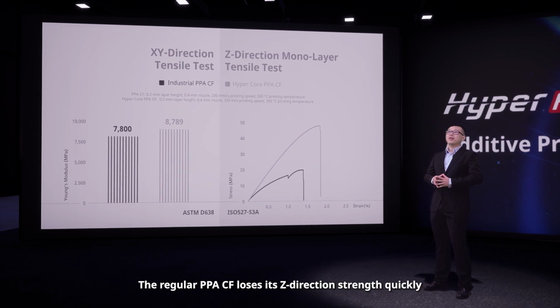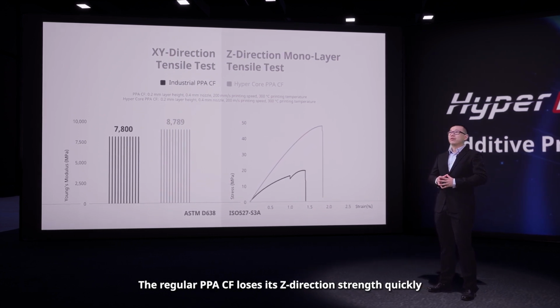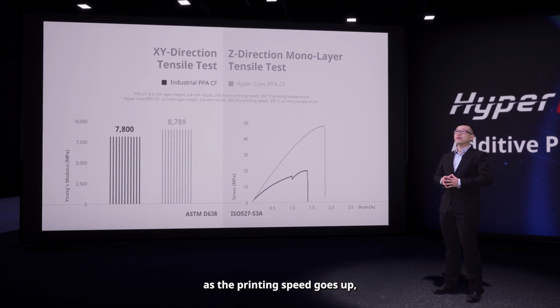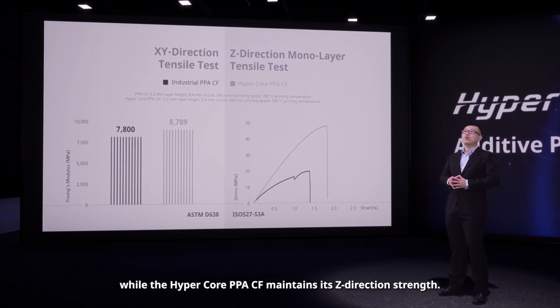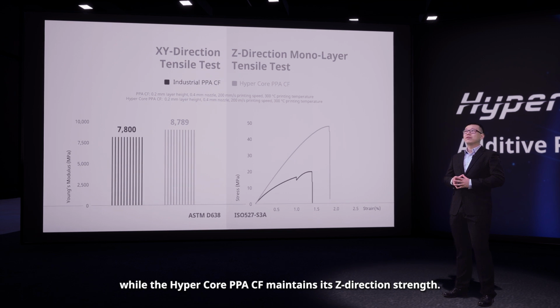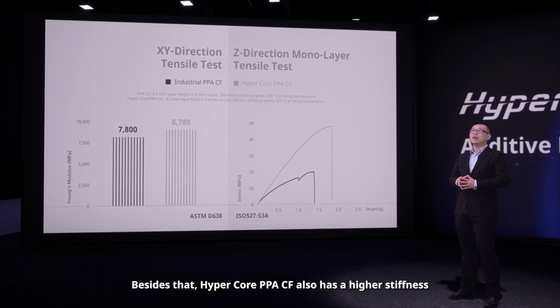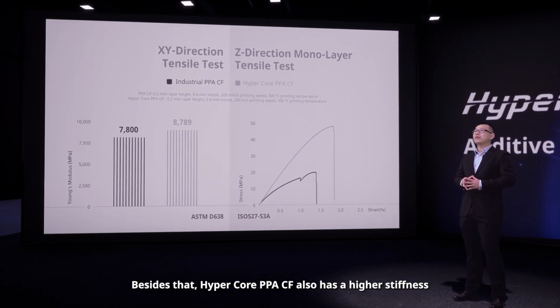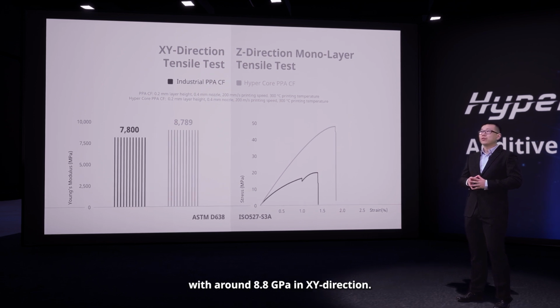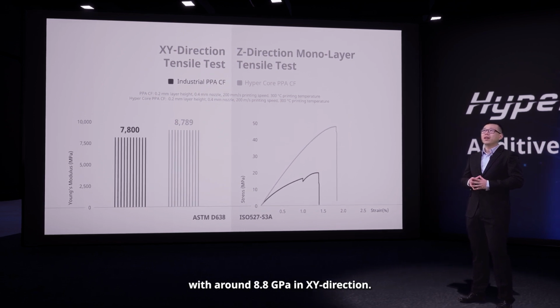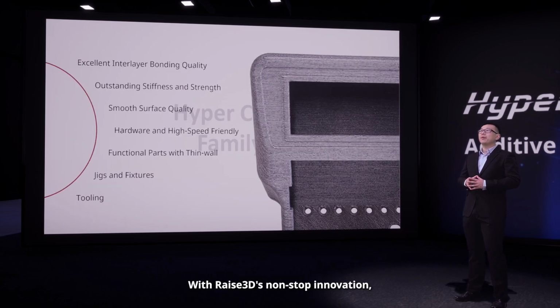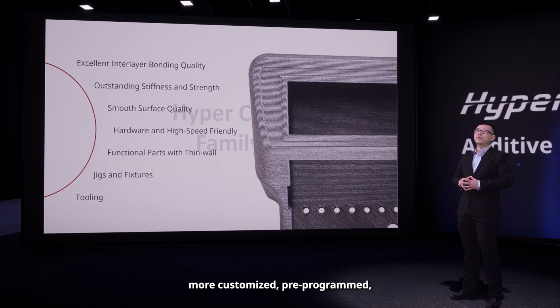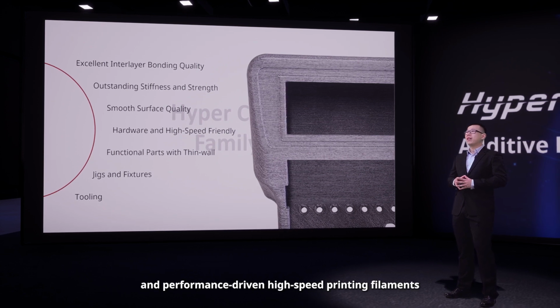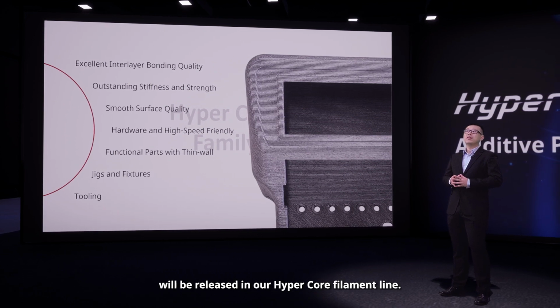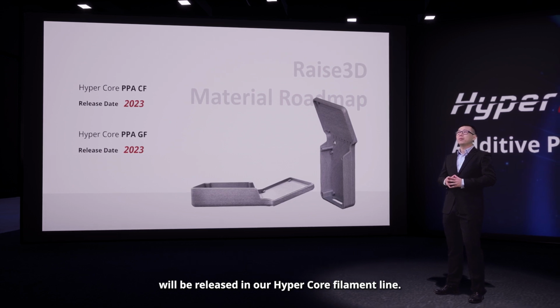The regular PPACF loses its Z-direction strength quickly as the printing speed goes up, while the HyperCore PPACF maintains its Z-direction strength. Besides that, HyperCore PPACF also has a higher stiffness, with around 8.8 gigapascal in X and Y directions. With Raise3D's non-stop innovation, more customized, pre-programmed, and performance-driven high-speed printing filaments will be released in our HyperCore filament line.